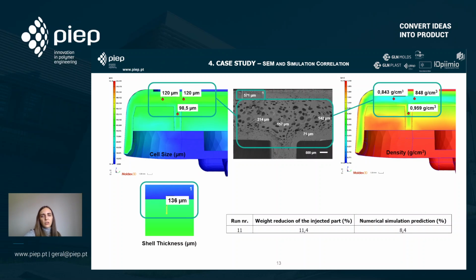And finally, we went on to a final section of the part from the analysis I showed before, and this is very interesting because we can clearly see different densities in the cell in the part. What we can see is that even for the shell in the lower section, we have some creation of cells in this shell, and it is replicated in the simulation. We can see the creation, the lower density in this case than the others I showed before. Once again, the cell size could not at all replicate the real setup.